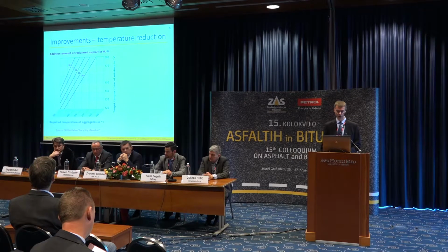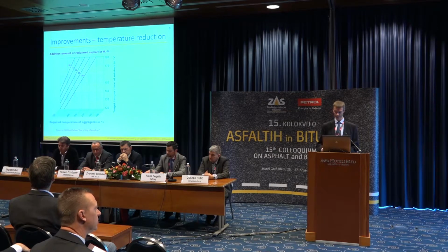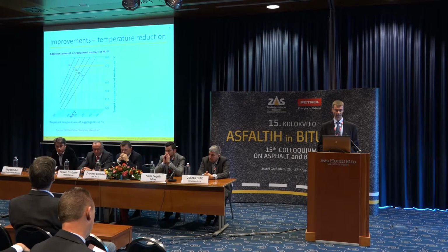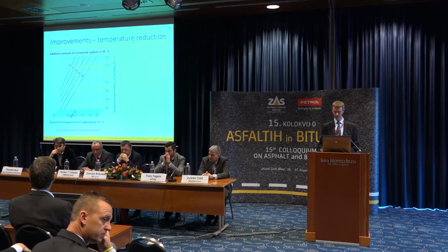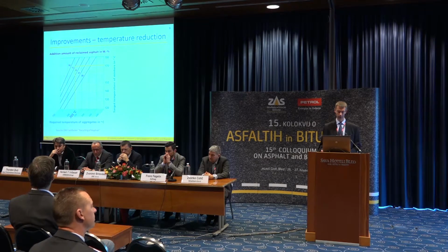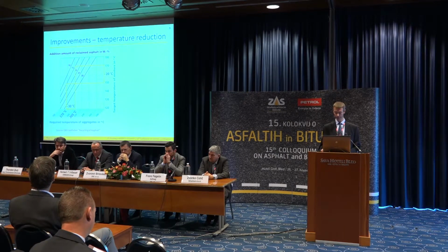Coming back to this temperature diagram, I would like to discuss the temperature reduction using FT wax. If we again have a target temperature for the asphalt mix of 170 degrees and add 15% RAP, we need 205 degrees for the fresh aggregates. Adding FT wax allows us to reduce the temperature by 30 degrees, and that results in 175 degrees, or in other words, 30 degrees lower temperature for the fresh aggregates. And this lower temperature has several benefits.